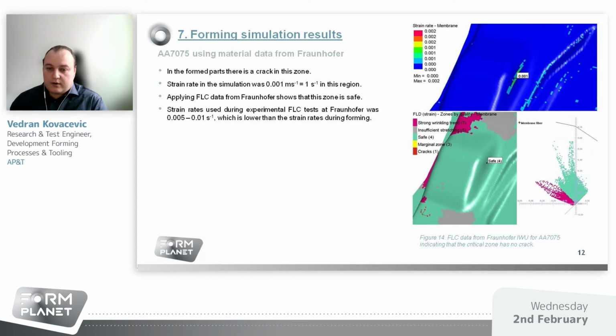In the region where the crack occurs, in the simulation, there is a strain rate of 0.001 per millisecond. Since the time unit system in PAM-STAMP is milliseconds, this equals a strain rate of 1 per second. Applying the FLC data from Fraunhofer to the result shows that this zone is safe, which is not the case as the crack occurred here. And the reason for this is, as mentioned, the low strain rates used during their experimental tests at Fraunhofer, which is lower than the strain rate during the actual forming procedure.